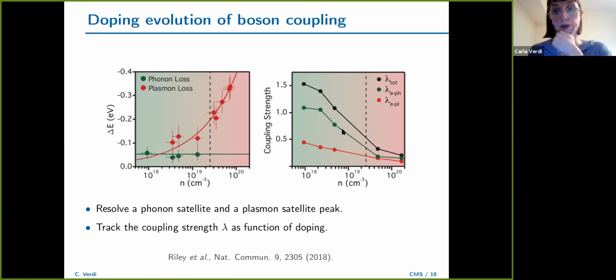The electron-phonon coupling decreases. And in fact, after this density level, you don't see the phonon loss peak anymore. So this is very interesting. Basically, it shows that in this material, you can really talk about phonon and plasmon polaron, and the coupling strength is even more tunable with doping.